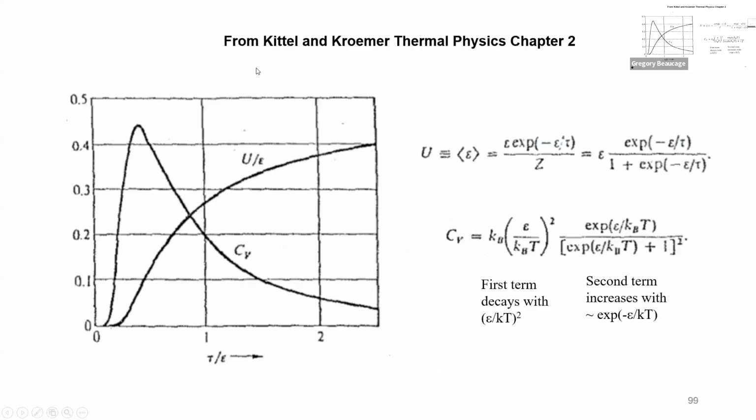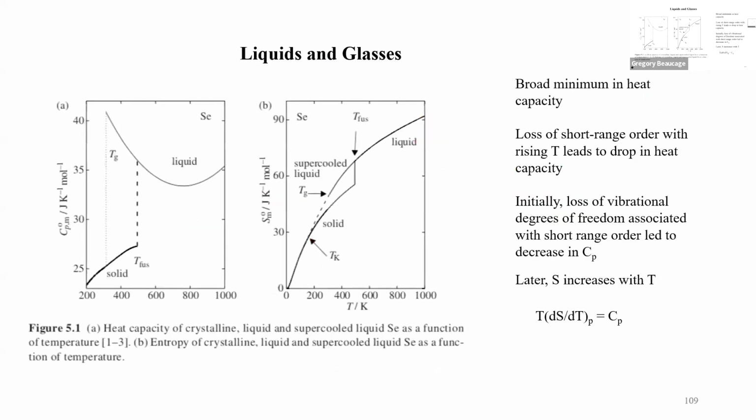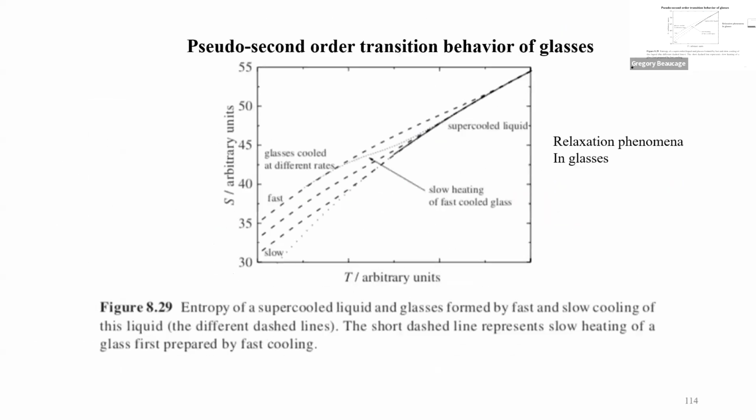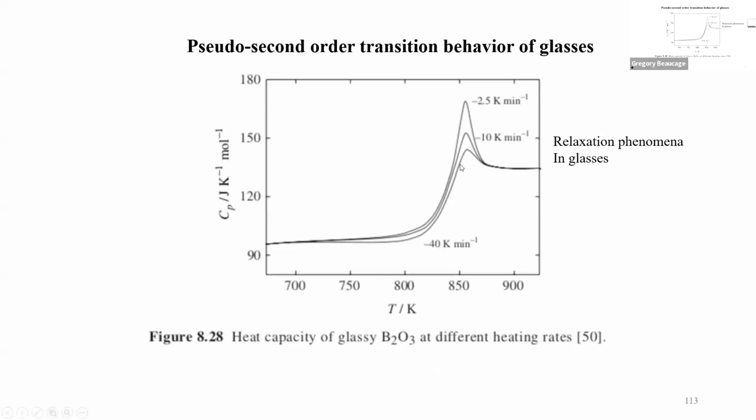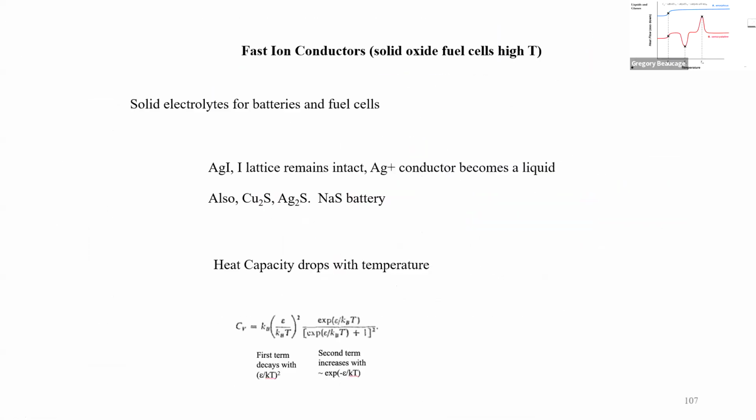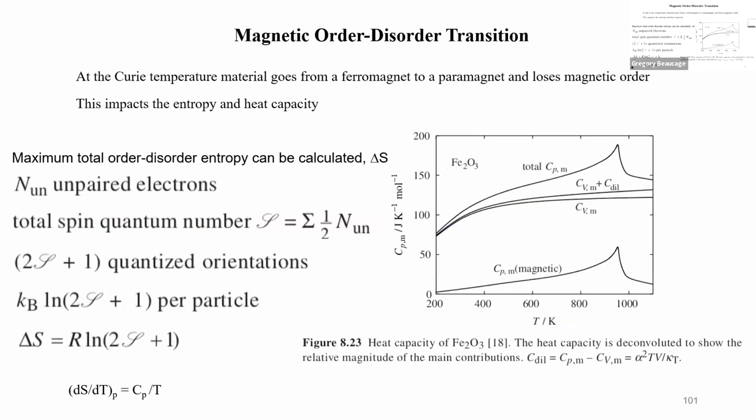So there's a plot of that somewhere here. Someplace here. Here. So these are different cooling rates. Oh, I guess this looks like it's backward, but the faster cooling should have a bigger peak on it. It looks like these are backwards, but basically the faster cooling has a bigger residual relaxation, whatever. So the slow cooling, it'll eventually get to no peak in it. That's for boron oxide glass. But anyway, so there's that business. Let me go back here.